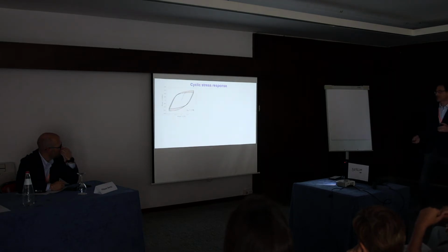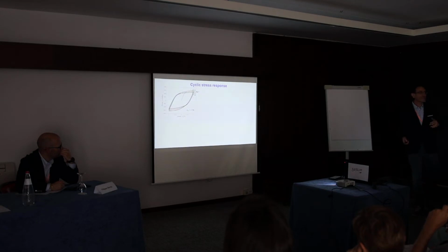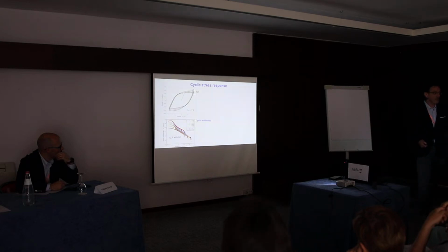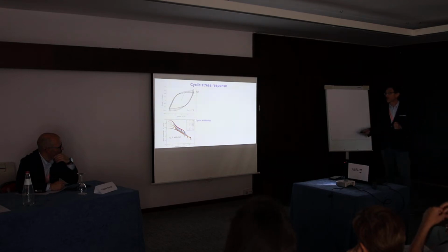First of all, this is an example of a stress-strain cycle, and as you can see here, there is a decrease in the peak stress. So this material exhibits a softening behavior, as also observed in the first presentation. And this softening behavior occurs in all of the tests.